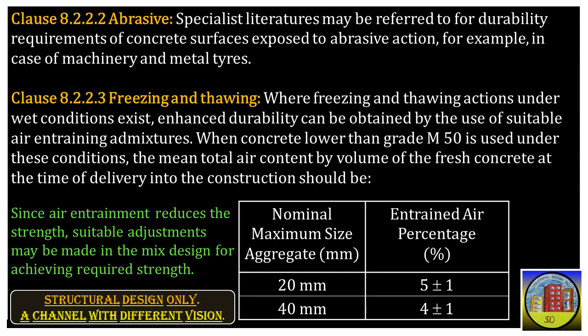Enhanced durability can be obtained by the use of suitable air entraining admixtures. When concrete lower than grade M50 is used under these conditions, the mean total air content by volume of the fresh concrete at the time of delivery into the construction should be: when nominal maximum size of aggregate is 20 mm, expected entrained air percentage, 5% plus 1 or minus 1%. When nominal maximum size of aggregate is 40 mm, expected entrained air percentage, 4% plus 1 or minus 1%. Since air entrainment reduces the strength, suitable adjustments may be made in the mix design for achieving required strength.